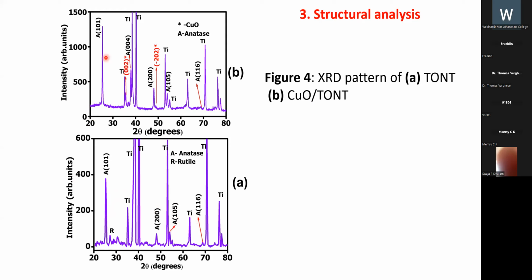In addition to these intense peaks, low reflection peaks are observed around 35.6 degrees and 48.8 degrees in the CuO/TONT structure. These are identified as the reflections from the 002 and 202 planes of copper oxide, and it indicates the formation of both copper oxide and TiO2 phases.